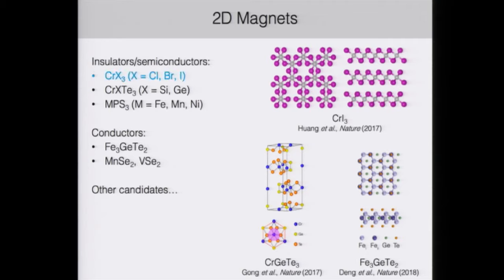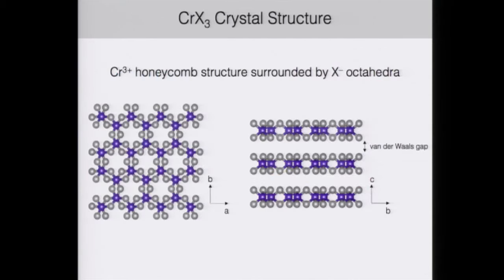For the rest of the talk, I'm going to focus on the chromium trihalides, which are a class of magnetic insulators. The chromium trihalides share a common crystal structure, where we have a chromium 3+ honeycomb structure, shown here in the purple spheres, surrounded by halide octahedra in the silver balls. Each monolayer is stacked upon other monolayers and separated by the van der Waals gap, which makes this a naturally layered, cleavable material.